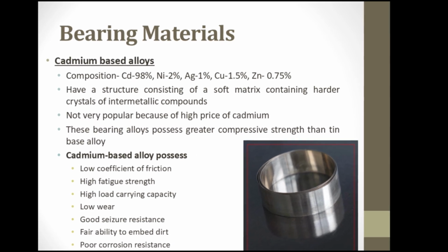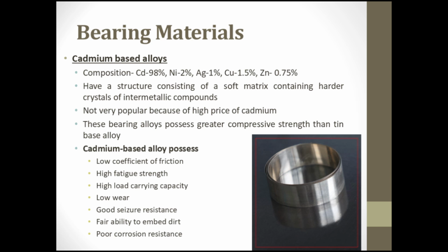Bearing materials: cadmium based alloys. Composition: cadmium 98%, nickel 2%, silver 1%, copper 1.5%, zinc 0.75%. Have a structure consisting of a soft matrix containing harder crystals of intermetallic compounds. Not very popular because of high price of cadmium. These bearing alloys possess greater compressive strength than tin based alloy. Cadmium based alloys possess low coefficient of friction, high fatigue strength, high load carrying capacity, low wear, good seizure resistance, fair ability to embed dirt, poor corrosion resistance.